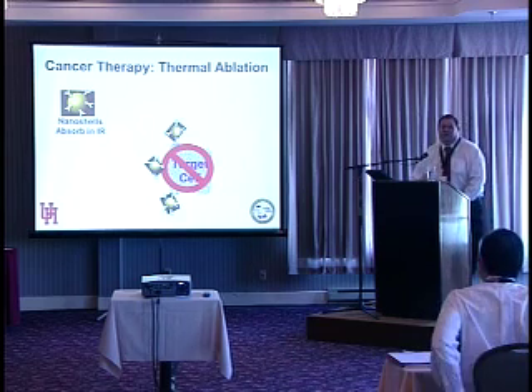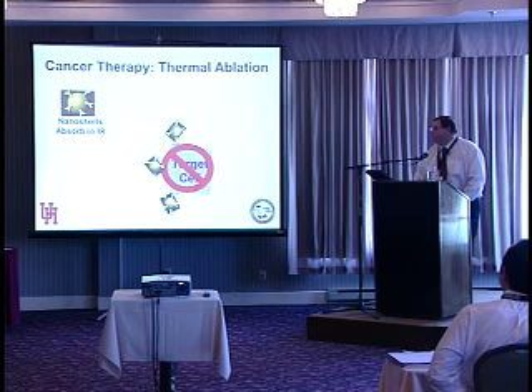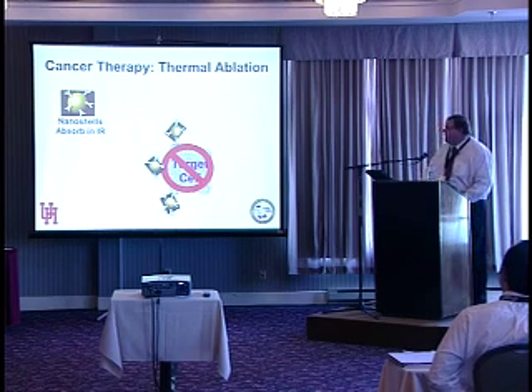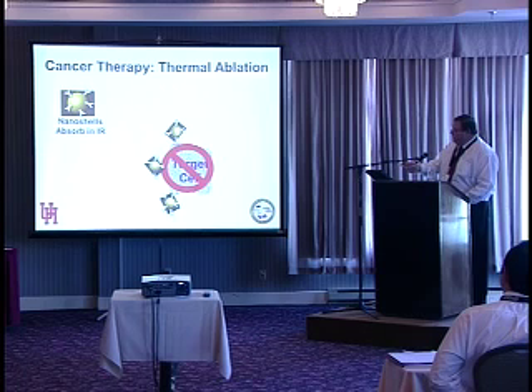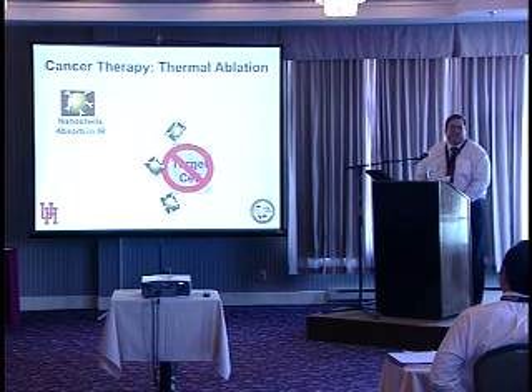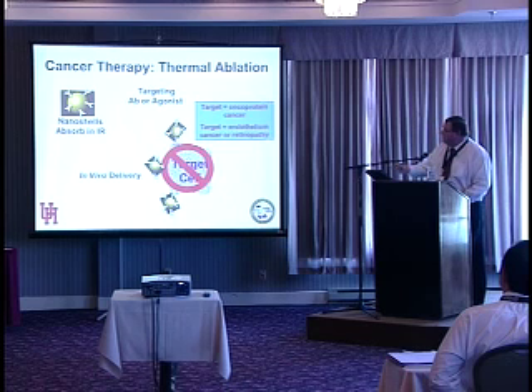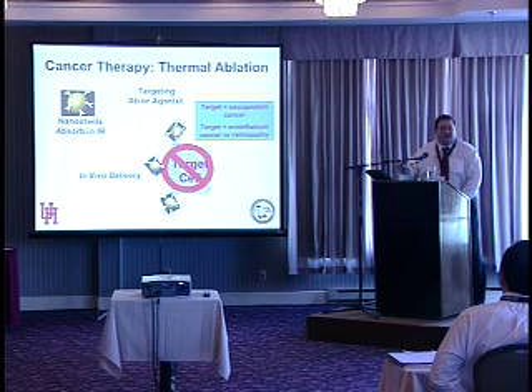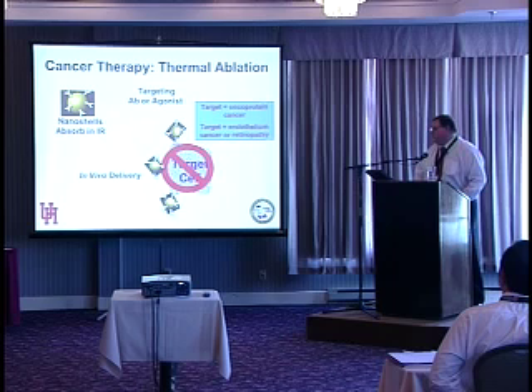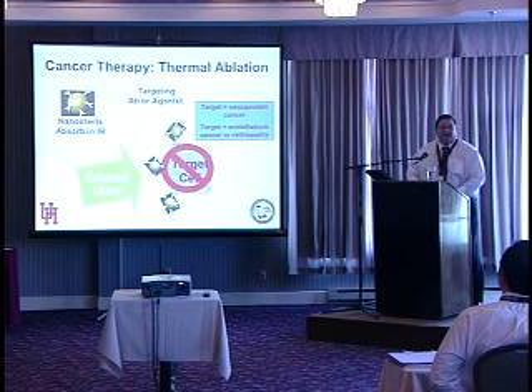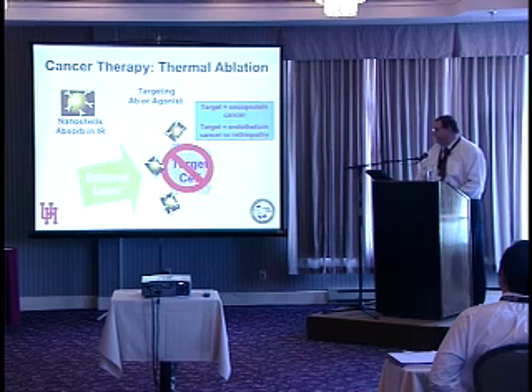Perhaps the application in which these nanoshells have received the most publicity is in cancer therapy. And so, for example, since nanoshells absorb in the near infrared and they have a gold surface, it's quite easy to conjugate an antibody or a targeting agent to the surface of the nanoshells, and then add the nanoshells to a target and either allow them, through the targeting agent or through the increased vascularization near the tumor, to build up in higher concentration than in normal cells. Then apply your external laser and then kill the tissue through optical heating.